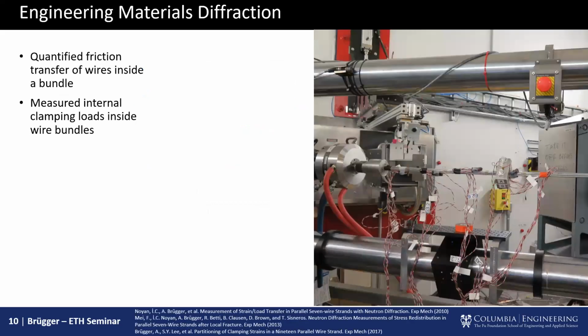But of course, the issue is that we only get that measurement in 1 gauge volume. So it's literally a little cube or cuboid inside the material. And for us to understand a larger 2D or 3D specimen, we have to actually step through the material and measure at various points. And that can take minutes or hours per point. So it's quite tedious and quite slow. So if you want to do dynamic measurement, this is very tough. You can do dynamic measurement of 1 spot only.